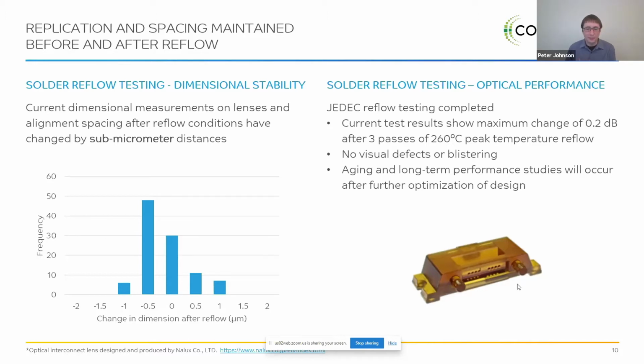We've also done this where we connect it to the optics to prove the validation, and we see that there's a fairly low change in the signal loss even through that entire reflow set. We don't see any visual defects or anything like that. And we're currently going through all the aging and long-term performance studies. That, of course, takes a lot longer. And we want to make sure that this is robust for a very long time, because while it is based on Ultem resin, we still want to make sure that everyone's comfortable with how the material performs. And we're going to show some of that data at the end.